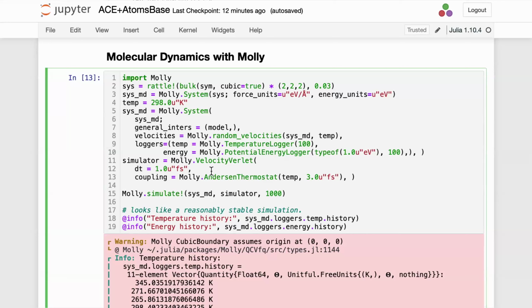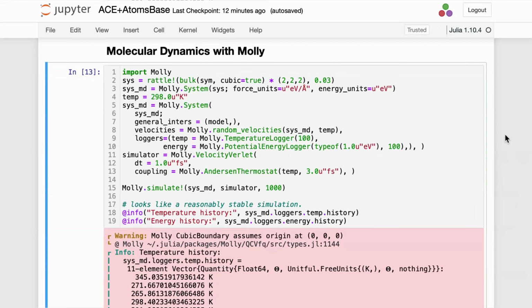In this case, because we have copper, you can use 2 femtoseconds or even 3 probably. Basically, you have to know the fastest motion of the system. Hydrogens vibrate harmonically on the femtosecond time scale, so you can't go any higher than a femtosecond, because hydrogen's so light. So you basically have to have knowledge of what the fastest motion is in your system.